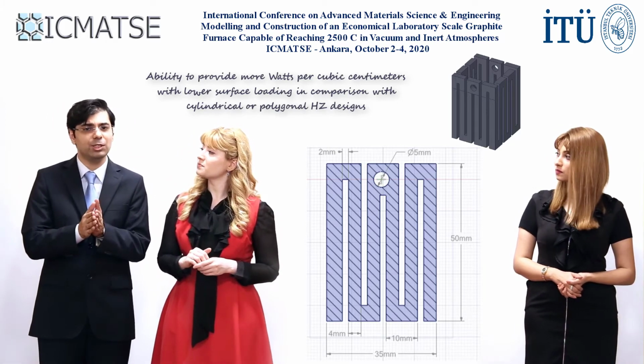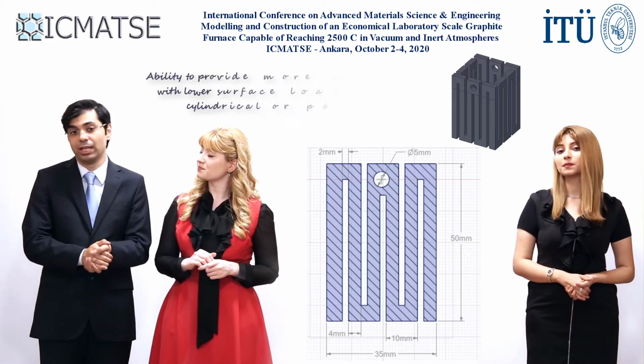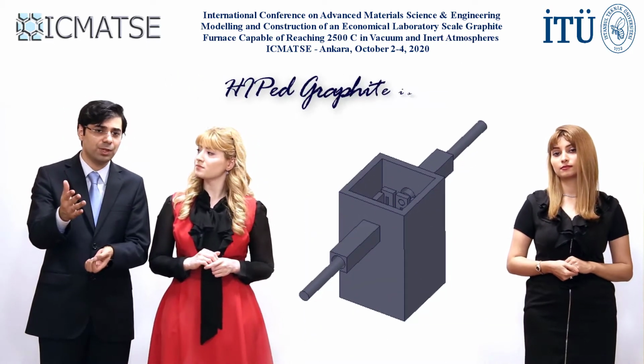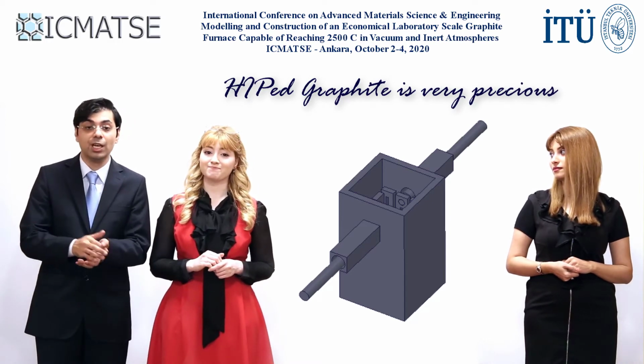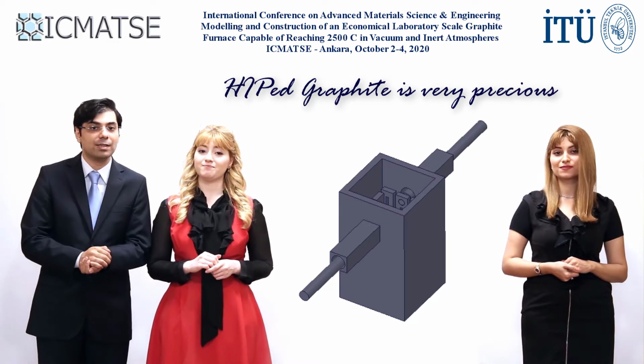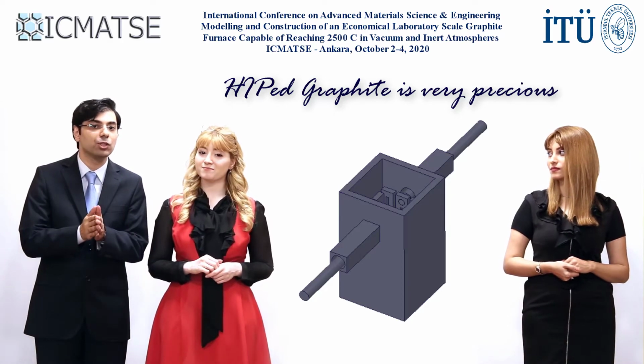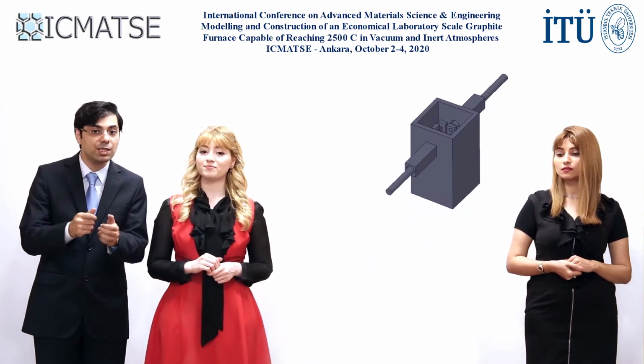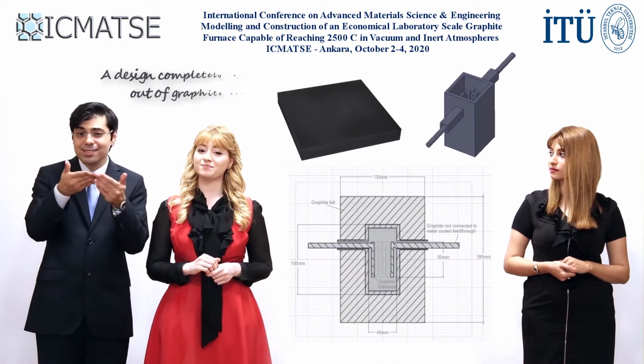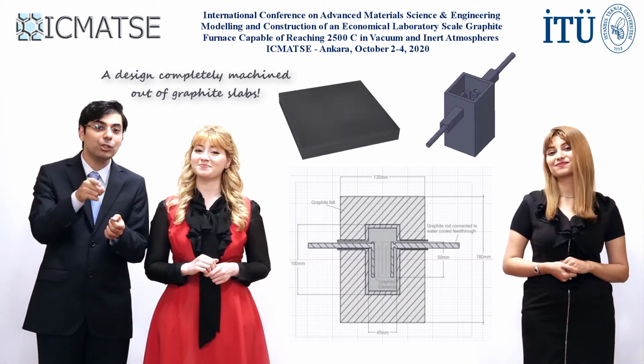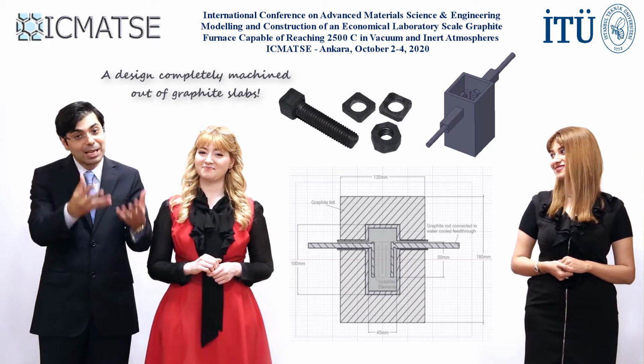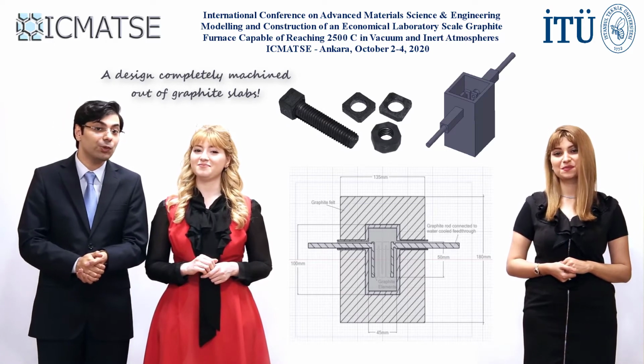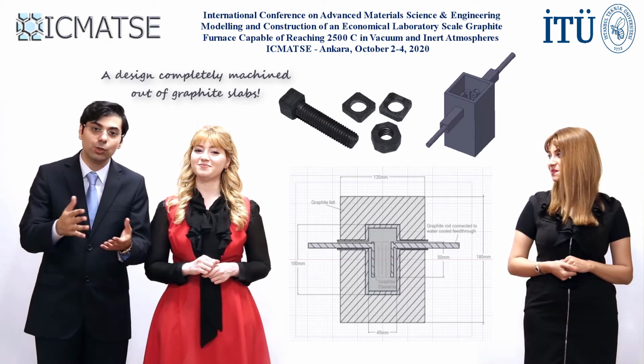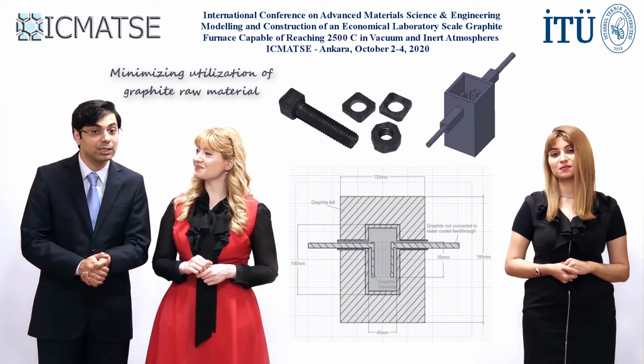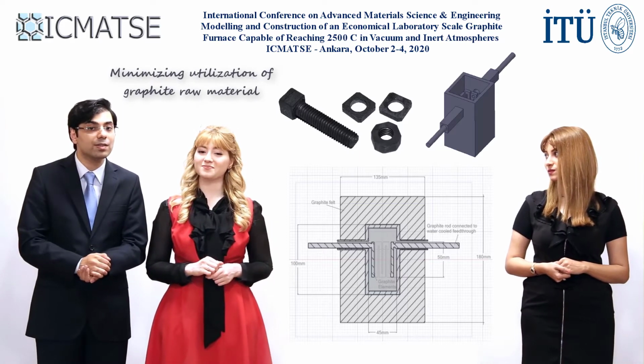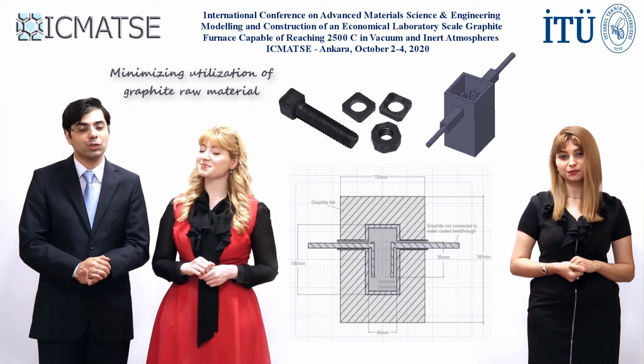Moreover, every cubic centimeter of high purity graphite which has been sintered at elevated temperatures using hot isostatic press technology is very precious. So it is only logical to minimize the consumed graphite during machining of the geometry required. Therefore, in the proposed design, it is possible to simply machine slabs of graphite and to connect them using nuts and bolts made from the same grade of graphite, minimizing the wastage during the manufacturing process. It is also noteworthy that a similar volume of hot zone constructed in the conventional cylindrical or polygonal designs consumes a significantly greater amount of raw material.